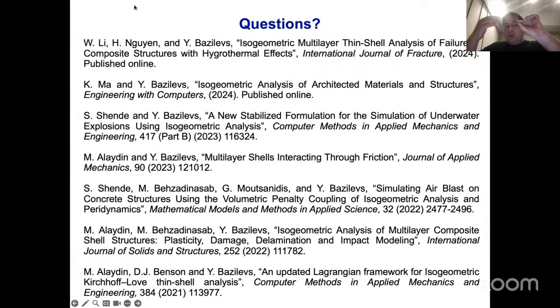So for example, if you were to use a solid element, for every layer you'd have to repeat. There's 1 displacement on top, 1 displacement on the bottom, so that doubles. See what I mean? And so you can dramatically reduce the number of degrees of freedom and still get the accuracy. In some of the examples with the laminates, a commercial code would run for a week, while we could produce results that are qualitatively the same or even better on a much smaller mesh with an overnight type calculation. I think this is where the opportunities are. I hope that answers your question.